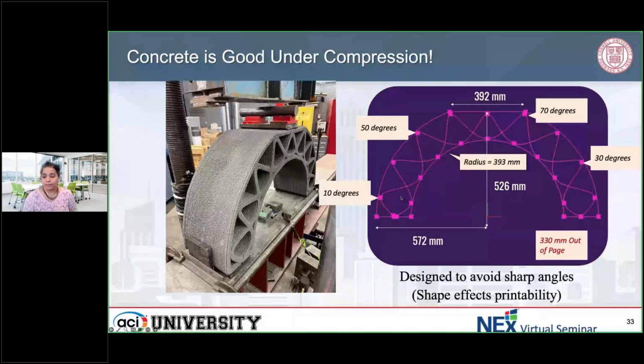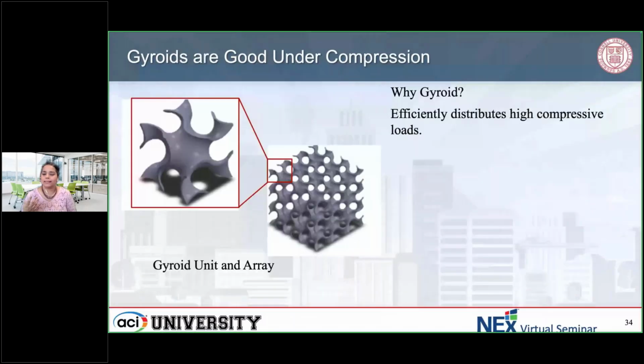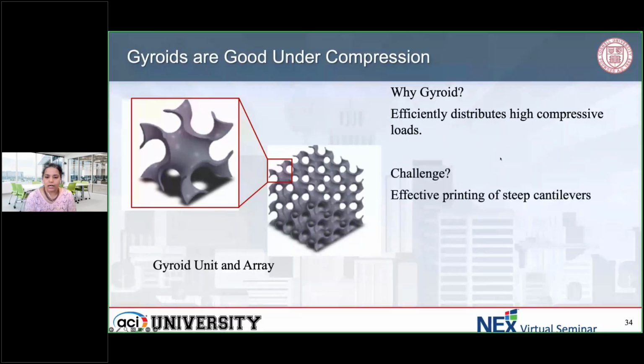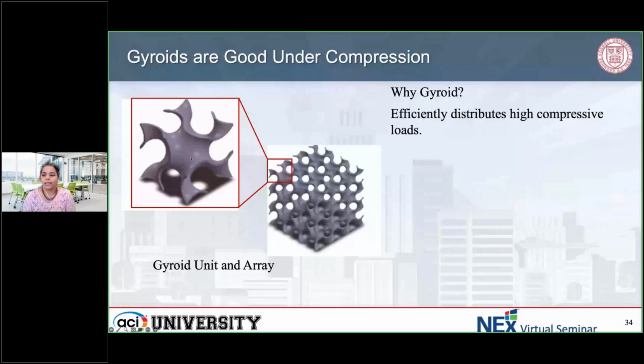So along that same theme, obviously you can all see that there's no reinforcement in any of the things we are printing right now. We are trying to maximize and see how concrete can be used in compression, right? So we are maximizing the material usage in compression. In general, when you look at what happens in nature, gyroids show up a few times, and they're supposed to be good in compression on all sides, and very efficient in distributing these compressive loads. But the challenge is that you have these cantilevers. For example, in the previous arch example, the same shape is printed over and over again. Similarly with these steps, it's the same shape printed over and over again. But when you look at this gyroid, the shape is changing. So if you were to 3D print this one, as you're going along that vertical height, each of them has a different layer system.